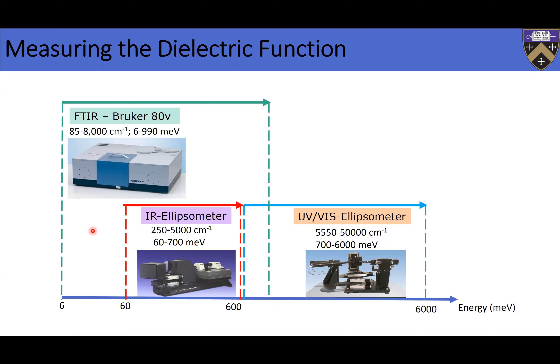I can go further using FTIR — Fourier transform infrared spectrometer. You can measure the reflectivity of the same sample you've done ellipsometry on, and through the reflectivity spectra, you can obtain the dielectric function. From general physics, free electrons reside in a certain range, phonons in another, and the rest is electrons. So by getting hold of the dielectric function, you are actually trying to understand how these phonons and electrons behave in your material.